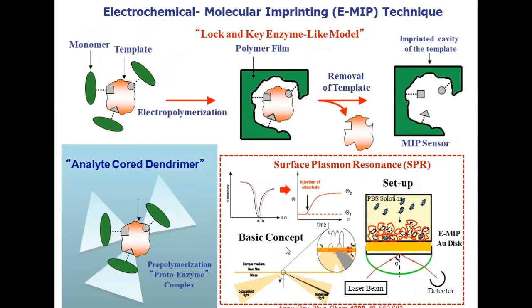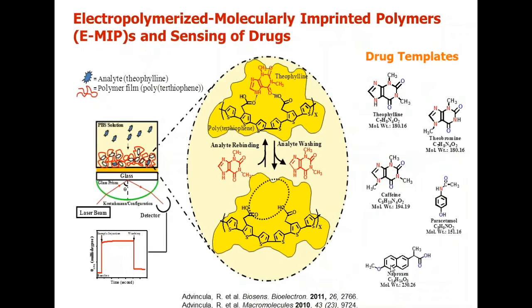The difference is that we again utilize those electropolymerizable monomers and print them on an SPR chip. This is a gold surface that is used for sensing or transduction based on an evanescent wave or irradiation that decays exponentially from the surface. This allows us to sense all the way to the nanometer level or nanomolar concentration. So this film, a biorecognition element, can be printed on the surface of your SPR. And here are some of the templates that we can print: theophylline, theobromine, caffeine, paracetamol. By polymerizing a terthiophene acid group around it, we can build this cavity and then sense the presence of these drug templates.